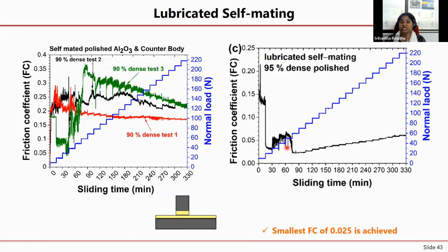But very interestingly, if you take the 95% dense specimen, then a friction coefficient as small as 0.025 is achieved. In fact, we have given these results to a Swiss watch company, and they found it very interesting. They were looking at that point of time at how to employ that in their industry.